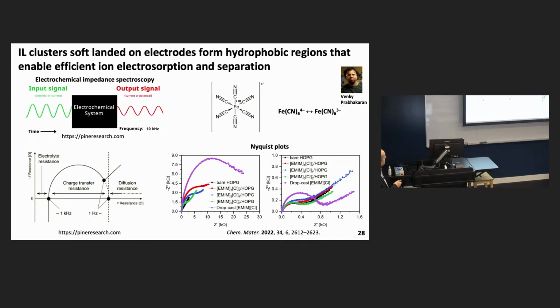In this case, we used iron ferrocyanide as a model system, and this allowed us to determine the charge transfer resistance both before, on the left-hand side, and after repeated cycling of these electrodes, which contain these ionic liquid clusters. And what I'll draw your attention to is how much reduced this charge transfer resistance is in the case where we soft landed these ionic liquid clusters. So we believe that this is a promising way to help increase the efficiency of ion separation from solution. And we think that we can actually further tune this behavior using the size of the ions, so 1, 2, 3, 4, 5, 6, and we'll be proceeding with that work in the future.